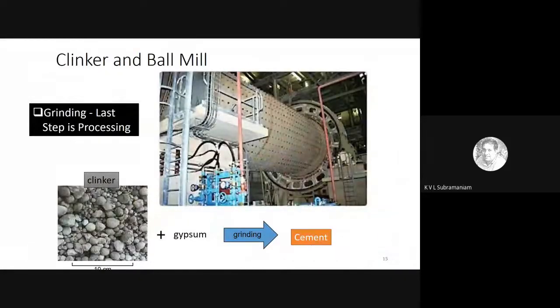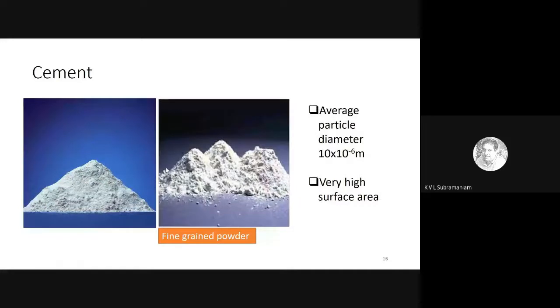Now after the kiln, what comes out is a clinker, and you see the clinker is basically in the form of these nodules. They're basically these grayish stone-like material, and that is then ground in a ball mill to produce a very fine material, which we call cement, this grayish powder. And of course, in the grinding stage is where we add gypsum to produce cement. And what comes out as cement is this grayish powder, the ordinary Portland cement, as we call it.